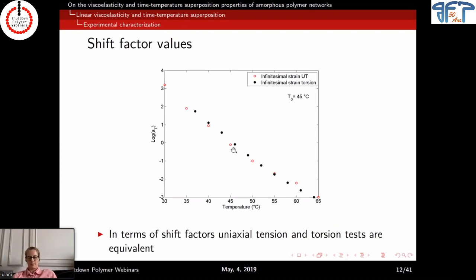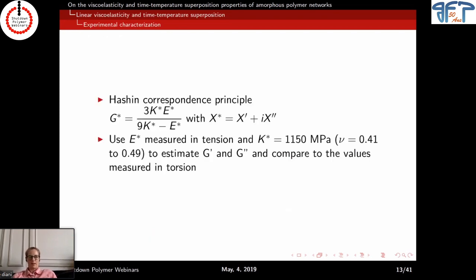shift factors. So both tests give us the same shift factors. If we want to compare G prime and G double prime for both tests, we can use Hashin's correspondence principle, which basically says that all the relationships that exist in elasticity still apply in linear viscoelasticity if you replace the elastic values by their complex values, which are defined as, for example, G star is going to be G prime plus i G double prime.